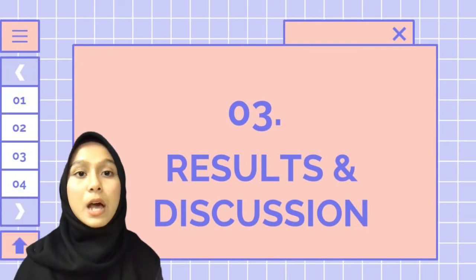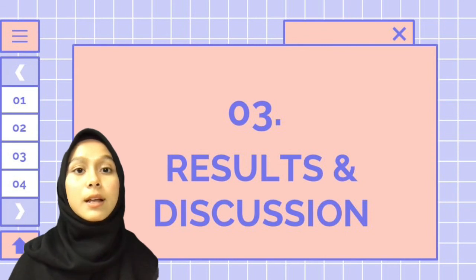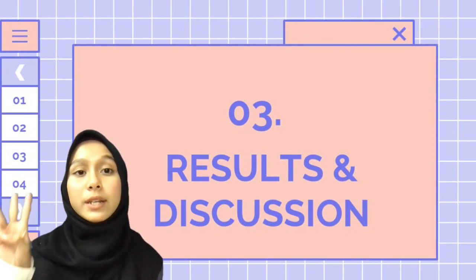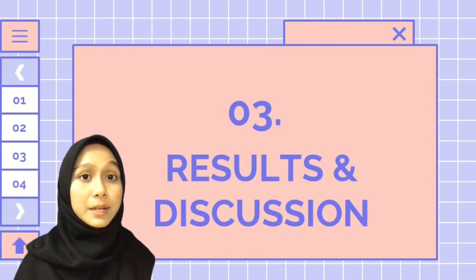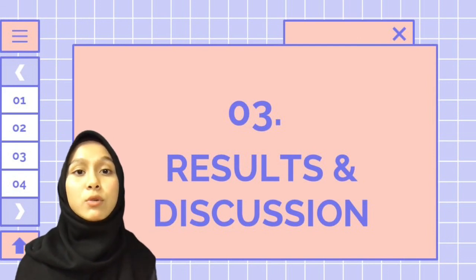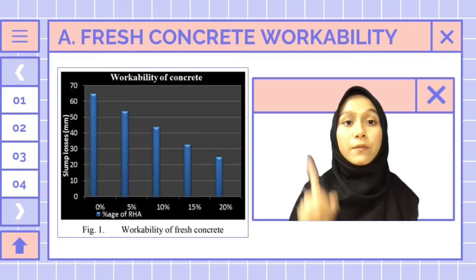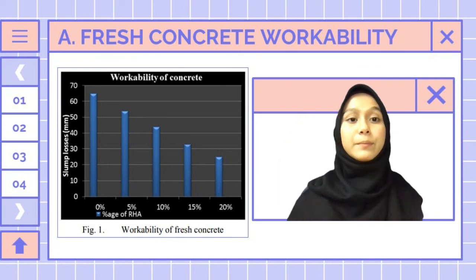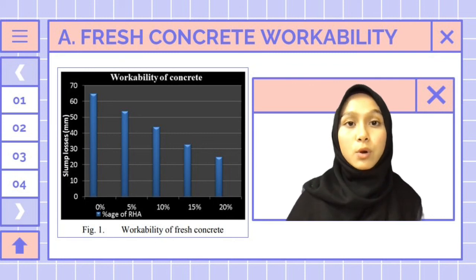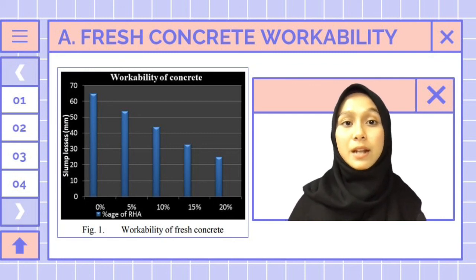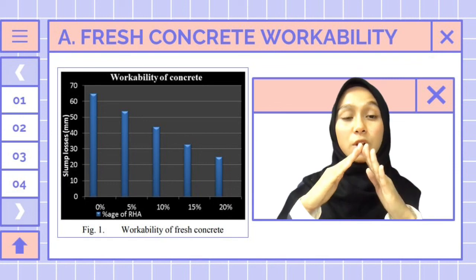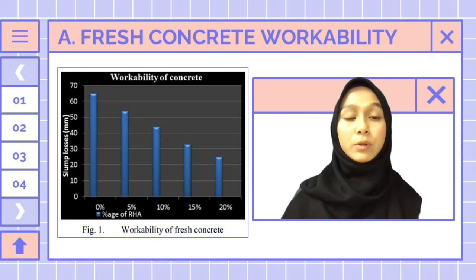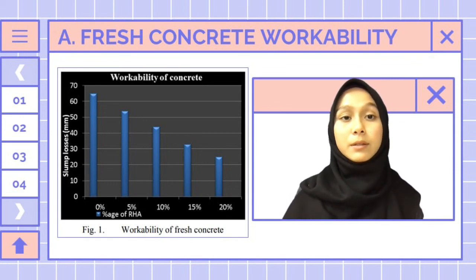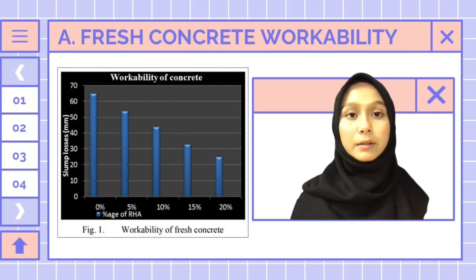The third one is I will describe the results and the discussion of this research. The findings are classified into three tests, which are Test A, Test B and Test C. So the data was tabulated in a graph. Firstly, they did an experiment to know the fresh concrete workability. A test of the flow of fresh concrete was conducted by slump cone. The dimension of the cone is 10 cm top diameter, 20 cm bottom diameter and 30 cm height.